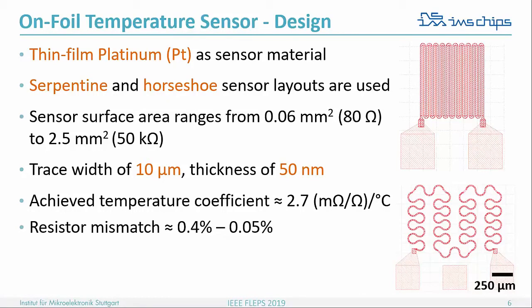And we achieved about 2.7 per degree Celsius of the temperature coefficient, and the mismatches between 0.4 and 0.05. The first number is for the serpentine design, and the second number is for the horseshoe design, which indicates that the horseshoe design somehow randomizes the process mismatch.